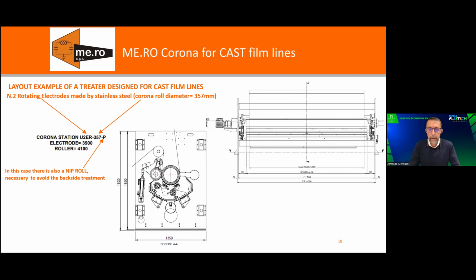As you can see, the structure and the design is completely different from a corona treater for a blown film line, because the power to be delivered on a cast film line, of course, is much higher. We go from 20, 25 kilowatt up to even 90 kilowatt on the 7-meter lines. So you need to use different electrodes, bigger electrodes, and bigger corona roll. The electrodes are in stainless steel. I will show you later on a following slide.